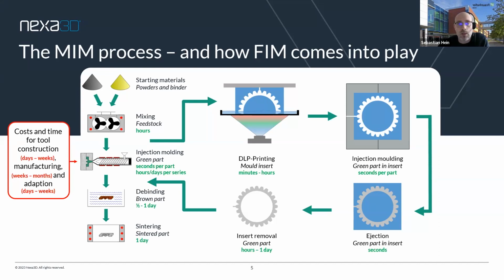It's simplified with just the inlet with a sprue, and if you print this and put it into your base mold, you can see that there's a line, the opening of the mold, which is the sprue, the gate, and there the feedstock comes in and fills basically everything, if you do it correctly, that was a cavity inside your printed mold, and then you can eject this as a block that is filled with the feedstock, and then you can remove this mold.